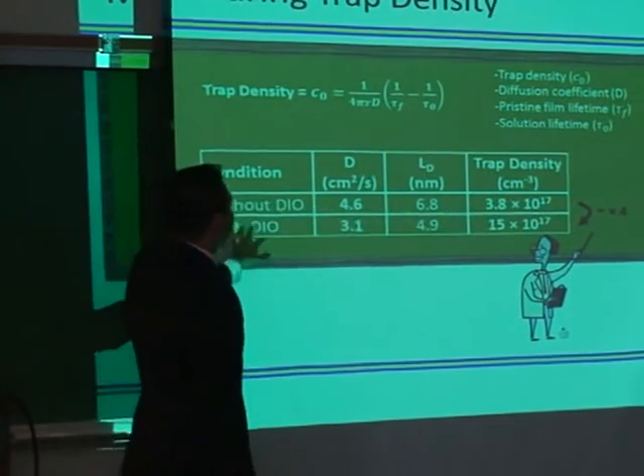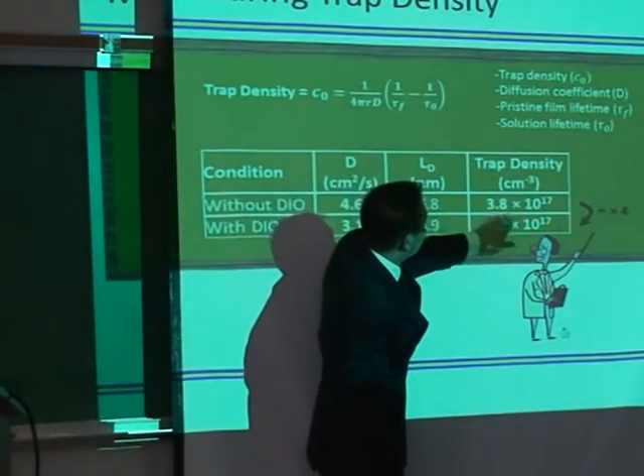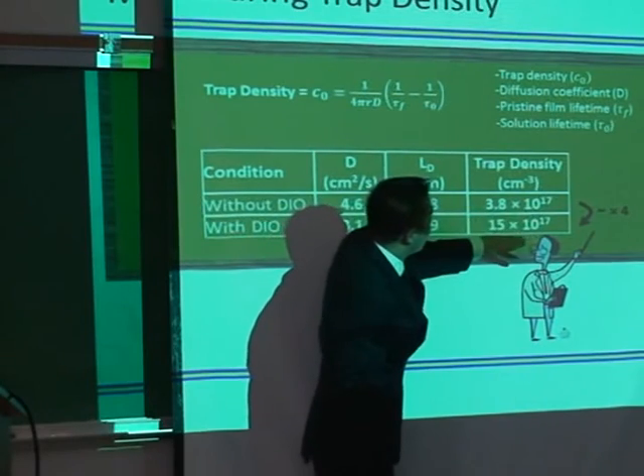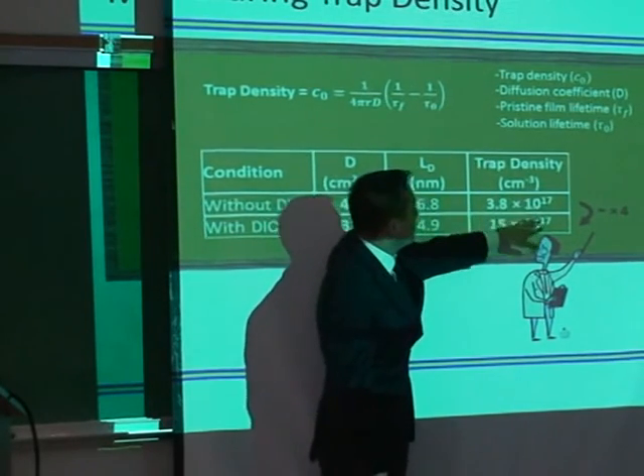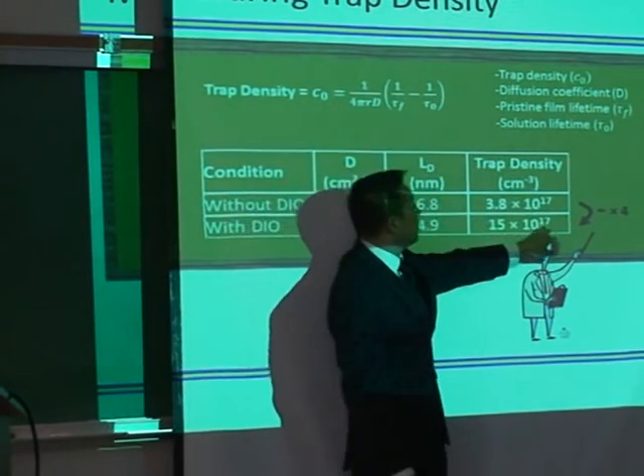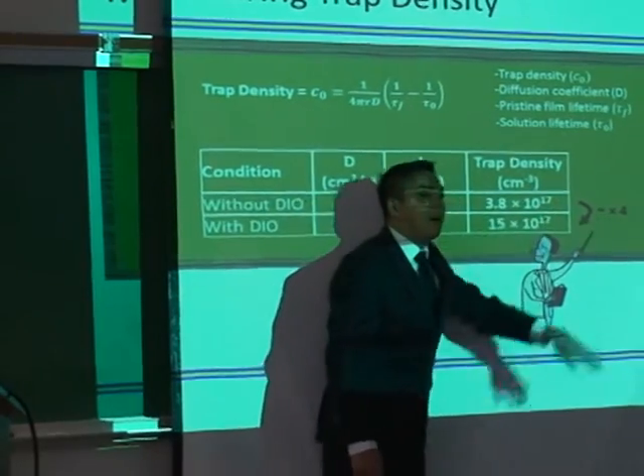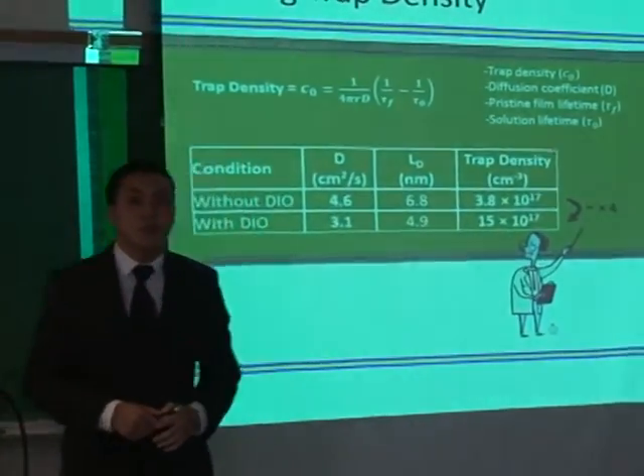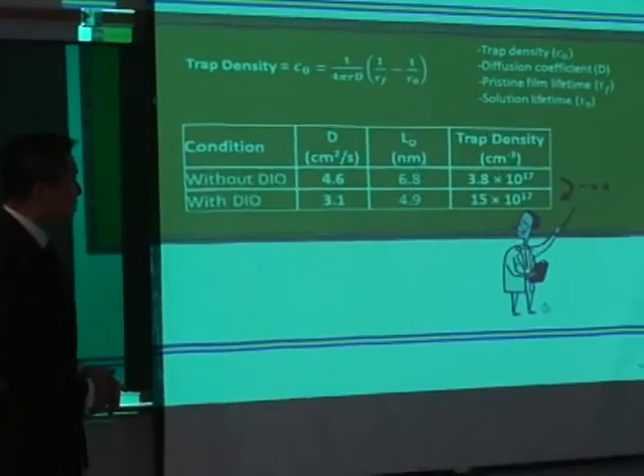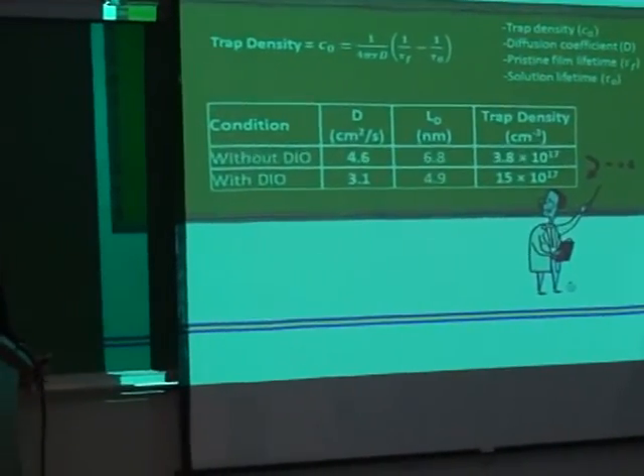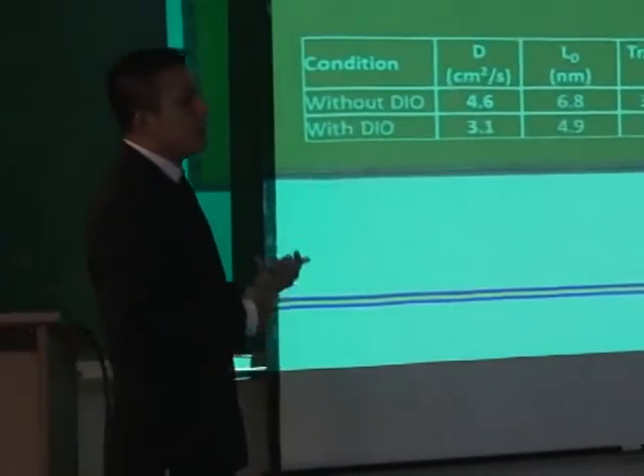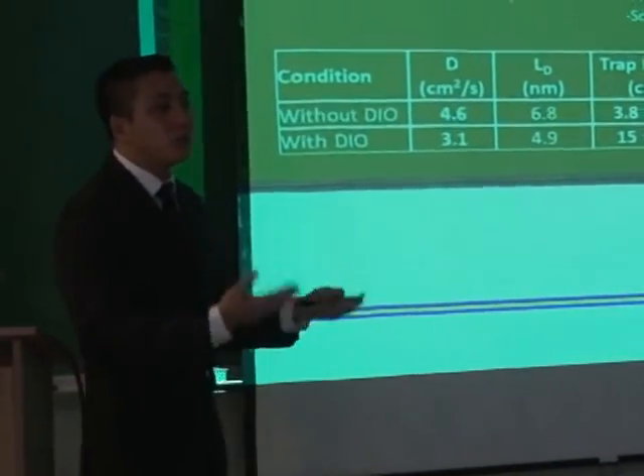In addition, what's also very interesting is that we found that the trap density increased from 3.8 times 10 to the 17 to 15 times 10 to the 17. And basically that is about a 4 times increase in the trap density. So both of those results were unexpected, but the nice thing is that it raises more questions for future work.